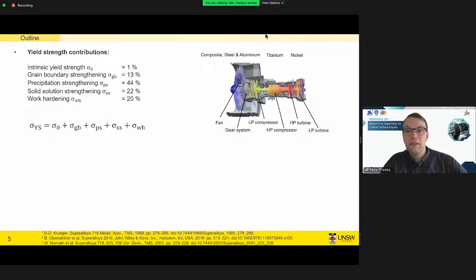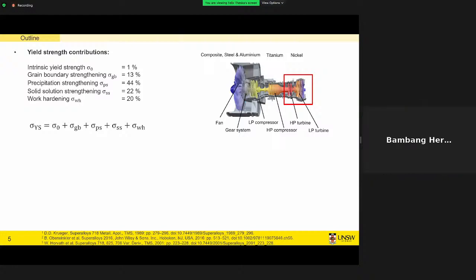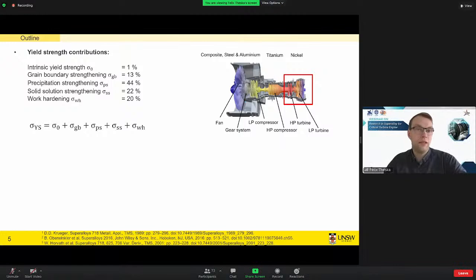Right, so we can look at the aircraft engine at the top right corner, and I just put a red box, but it's actually talking about the hottest parts of the engine. You've seen the chemical composition is quite complex for this alloy, and therefore the strength contributions are also quite complex. So we have the intrinsic yield strength, we get some grain boundary strengthening, that's our Hall-Petch relationship, we get some solid solution strengthening and work hardening, but most importantly is the precipitation strengthening. As you can see, it contributes about 44% of the yield strength.